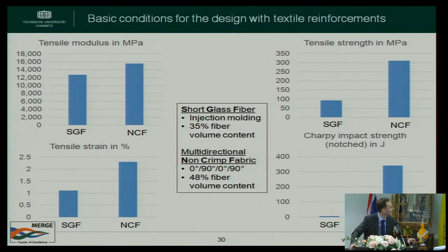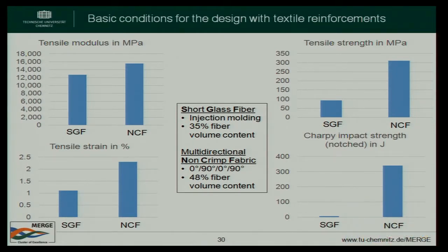But when you compare now the resulting properties in the part, you see short glass fiber, we are on this level, non-crimp fibers, we are on this level, so the difference is not so much in the stiffness, because already with short fibers, we reach quite a good level. When we are looking at the tensile strength, it's already a bigger difference. You see it here, let's say something between 30-35% compared to the non-crimp fabric. The tensile strain already increases, but the most difference you see in the impact properties.